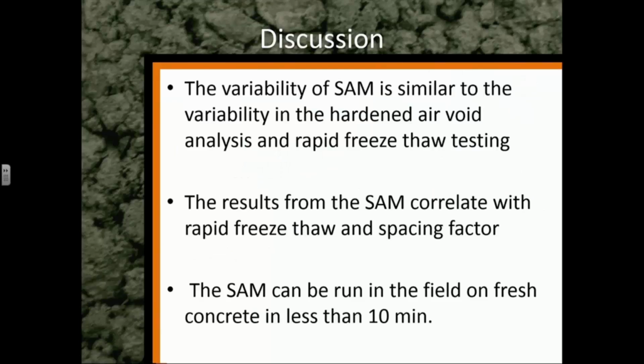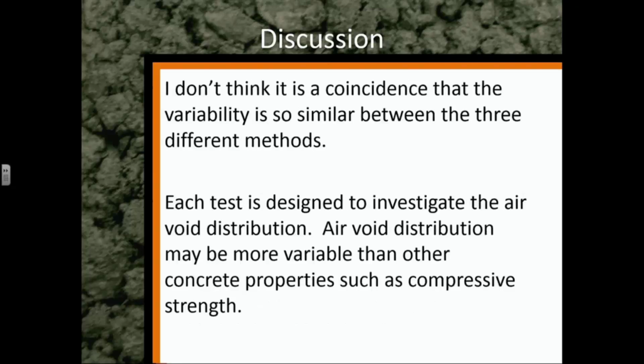So, what's going on here? The variability of the SAM is similar to the variability in the hardened air void analysis and the rapid freeze-thaw testing, and the results from the SAM correlate with the rapid freeze-thaw and the spacing factor. That's good. But the SAM can be run on fresh concrete in 10 minutes. There's a lot of advantages there, a lot of benefits. And I don't think personally that it's a coincidence that the variability is so similar between these three methods.